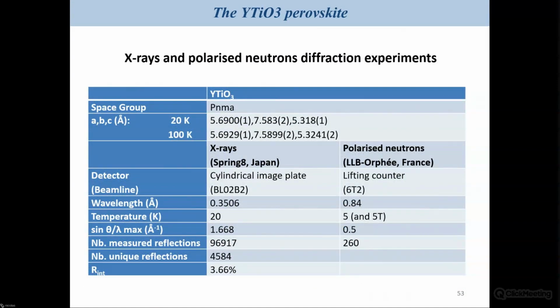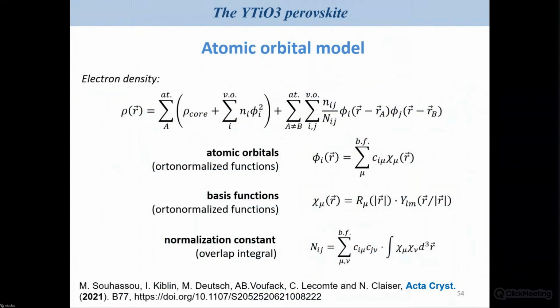made a specific X-ray diffraction experiment in SPring-8, Japan, in very good conditions because it was possible to reach very low temperature, and we have a very short wavelength, which is recommended if you consider the fact that you have yttrium and titanium in your compounds. So we have a very good quality dataset for that joint refinement. And on that occasion, we developed what we call the atomic orbital model.